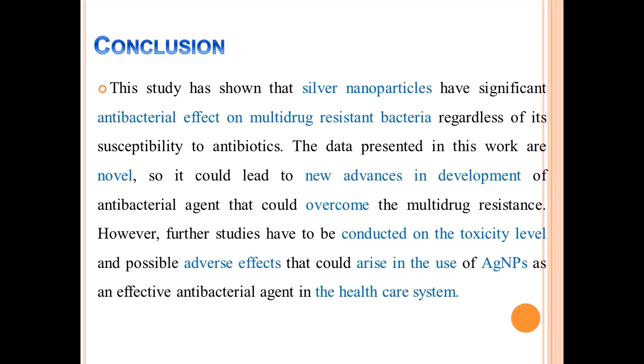Conclusion. This study has shown that silver nanoparticles have a significant antibacterial effect on multidrug resistant bacteria, regardless of their susceptibility to antibiotics. The data presented in this work are novel, so it could lead to new advances in development of antibacterial agents that could overcome multidrug resistance. However, further studies have to be conducted on the toxicity level and possible adverse effects that could arise in the use of silver nanoparticles as an effective antibacterial agent in the healthcare system.